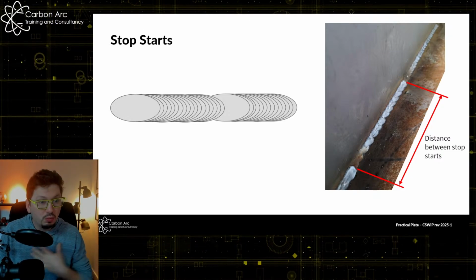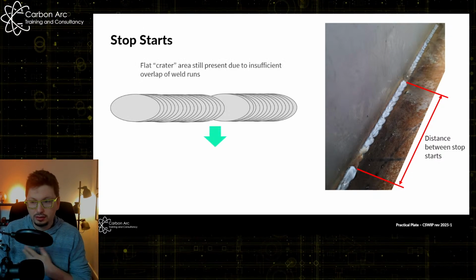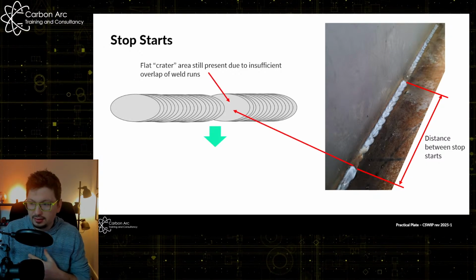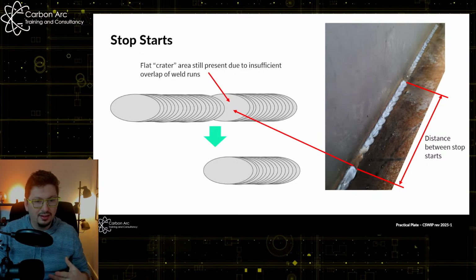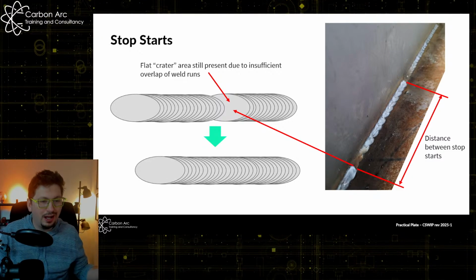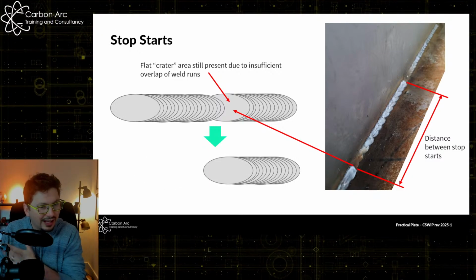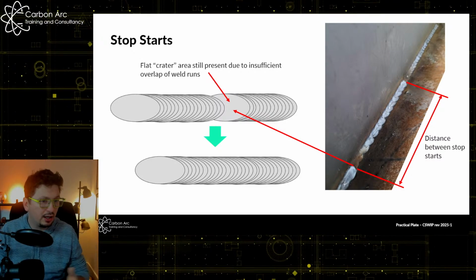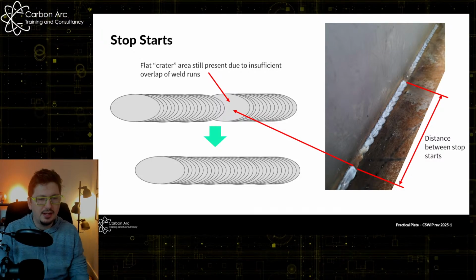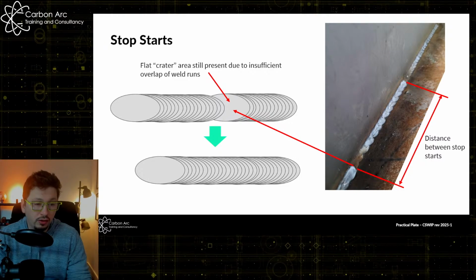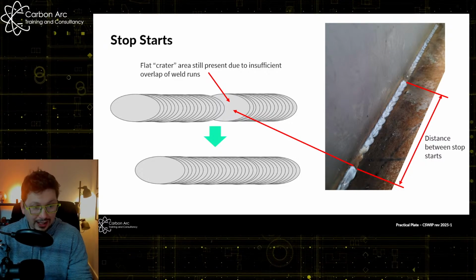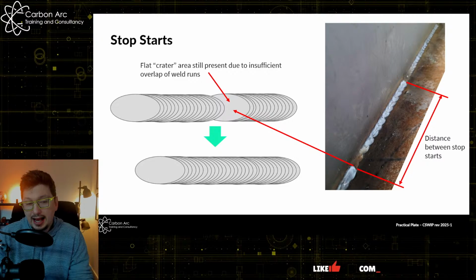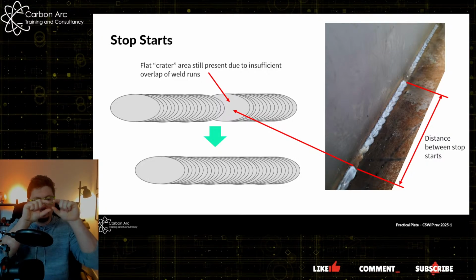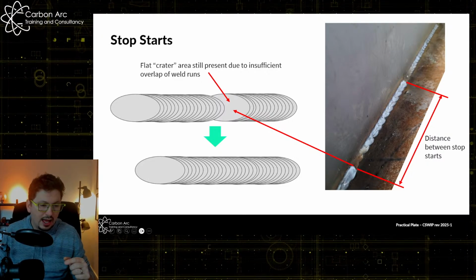So really what we want is to be able to weld, and then continue welding, so we lose that initial crater, so we have the overlap required. Now this is what it looks like on the cap of the weld, where if we had it on the root, what you would see is the weld coming along, and it would sort of thin out and then come back up again.